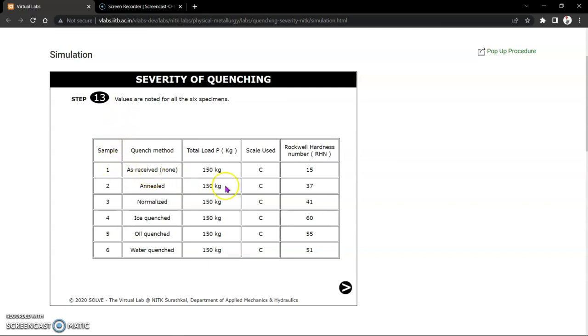Sample 1, as received, Rockwell hardness number is 15. Sample 2, annealed, Rockwell hardness number is 37. For sample 3, normalized is 41. Sample 4, ice quenched is 60. Sample 5, oil quenched is 55. Sample 6, water quenched is 51.